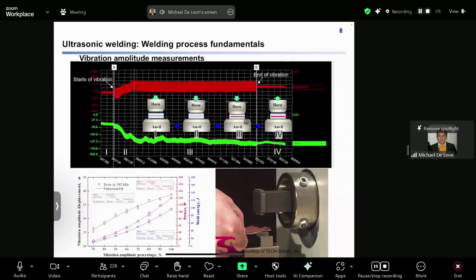These are the vibration amplitude displacements at different percentages. They tie directly to the energy and power delivered to the weld. In most cases, it ranges from 20 micrometer displacement to 40 micrometer displacement, and seldom exceeds 100 microns. The vibration amplitude is also an independent variable; it can be set and controlled at the power supply through a feedback control system.